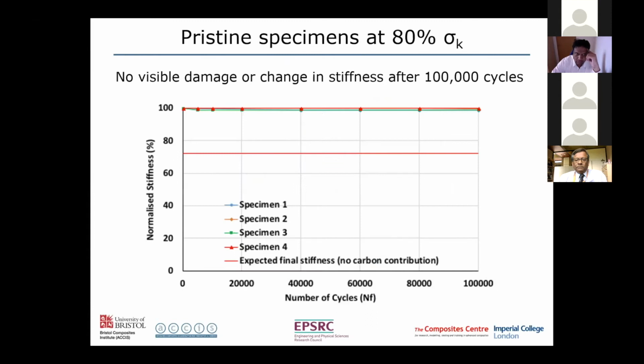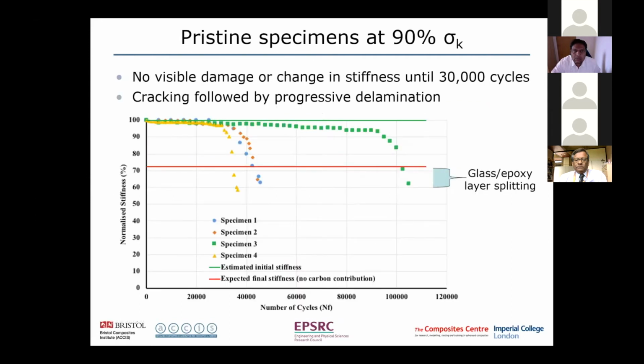You can see that at 80% of that knee stress, there's no visible damage or noticeable change in stiffness even after 100,000 cycles. So if you keep the stress below that pseudo yield point, then they're very good in fatigue. You take the stress a bit higher, then after some time you do start to get some failure. So at 30,000 cycles, at 90% of that knee point, you do start to see some failure, because at 90% of the knee point, there's already a little bit of damage in that carbon, and it does eventually start to spread.